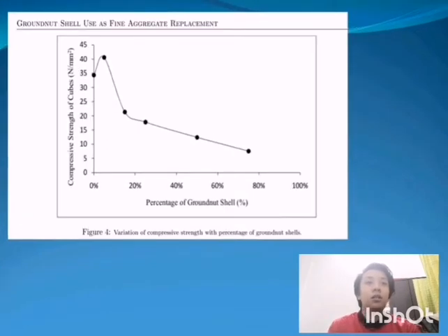This is the graph for percentage of groundnut shell and compressive strength of cube. For the compressive strength values obtained for the concrete specimens, as shown in figure 4, it can be seen that the strength of concrete decreased with an increase in groundnut shell percentage. It was observed that during soaking, the concrete cubes containing more groundnut shell, 50% and 75% replacement, may have absorbed more water, which led to low workability of the concrete mixture, and this contributed to the low compressive strength at this replacement level. Also, the low density of the groundnut shell compared to that of the fine aggregate it was used to replace may also have contributed to the low strength of the concrete.